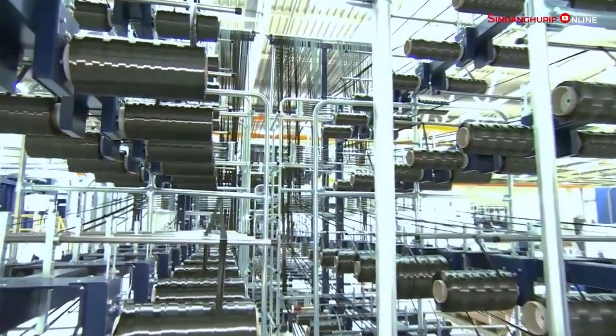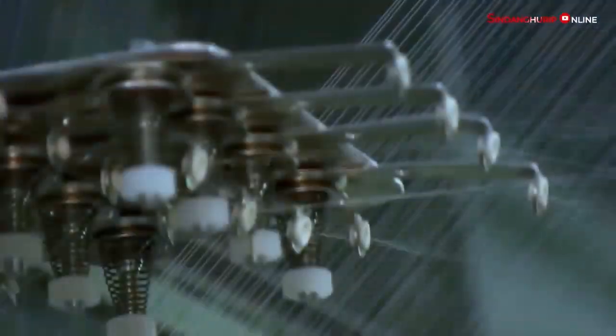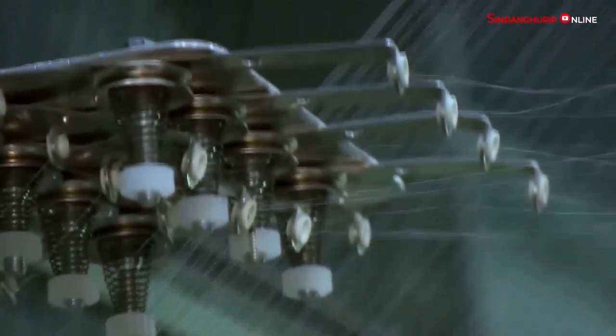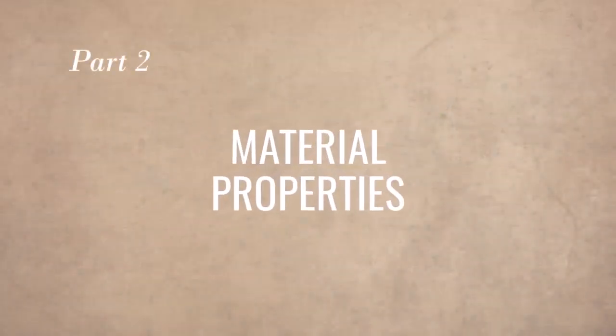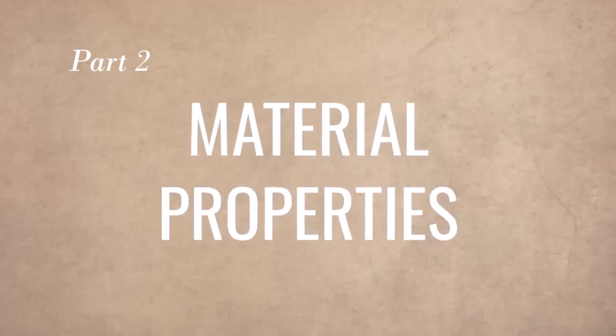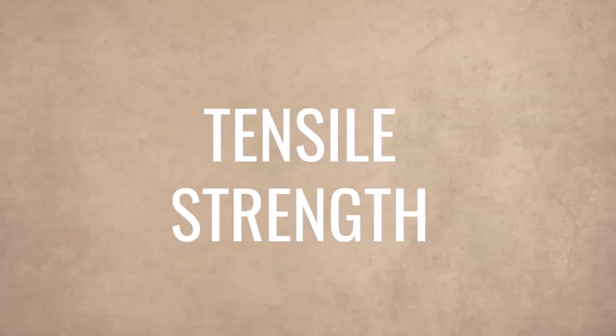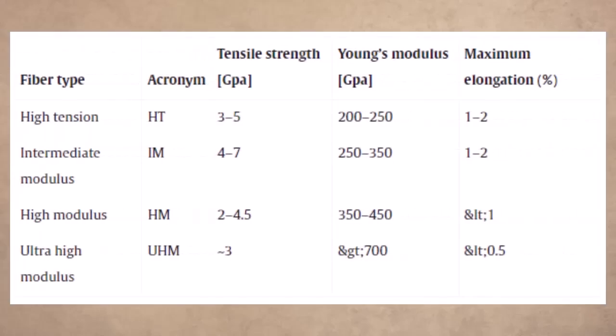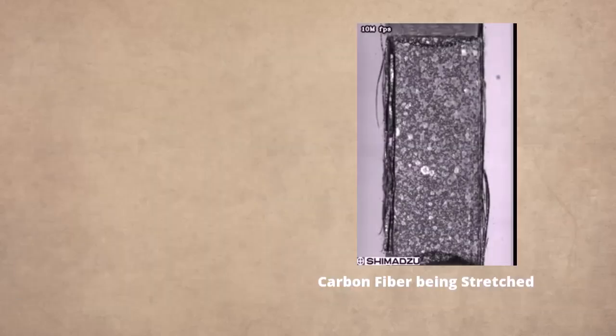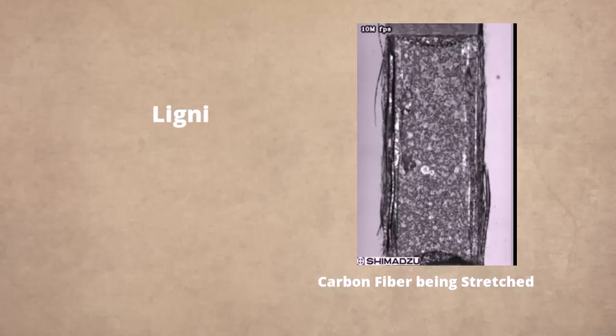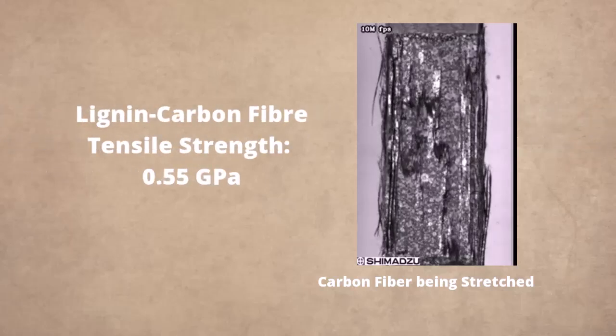In the production of carbon fibers, the manufacturing process plays a large role in determining the material properties. One material property of carbon fiber that is most important for their applications is the tensile strength. Looking into their tensile strength, traditional carbon fibers range from 3 gigapascals to 7 gigapascals. On the other hand, for lignin-based carbon fibers, their tensile strength only goes up to 0.55 gigapascals.